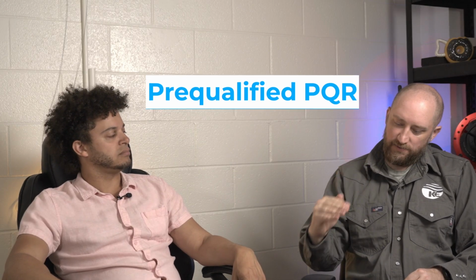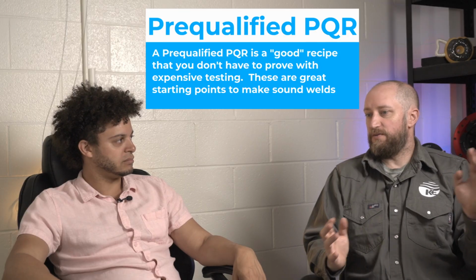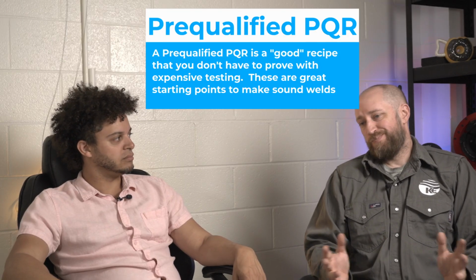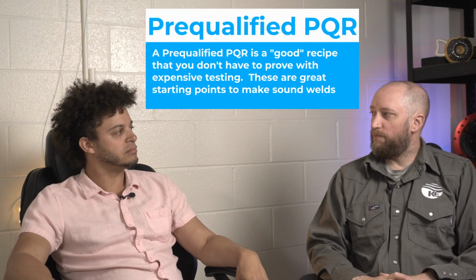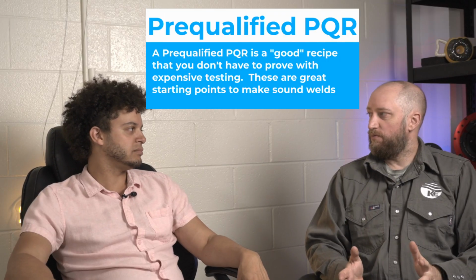Well, part of what you bring up there is the pre-qualification, where you don't have to run a PQR, you don't have to spend a couple thousand dollars to have a weld made and tested. The code says, if it is this joint design, this process, and these parameters, that's been made enough times in the industry that you're more than welcome to make this on your own, and you don't have to run a PQR to prove that it's okay.